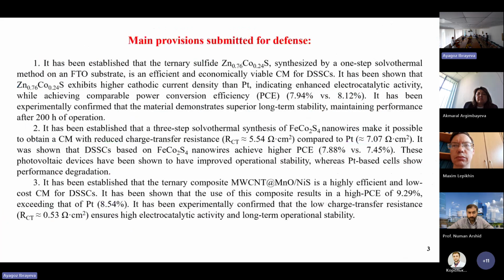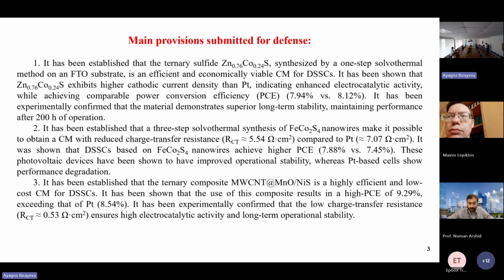Main provisions submitted for defense. First, it has been established that the zinc cobalt sulfide synthesized by a one-step solvothermal method on FTO is efficient for DSSC. This material demonstrated great long-term stability. The second, by another synthesis, it was established that iron cobalt sulfide nanowires work well compared to platinum, and also reduce charge transfer resistance. The third, a synthesized ternary composite of manganese oxide and sulfide with multiwalled carbon nanotubes showed higher efficiency than platinum. It has been confirmed that the low charge resistance provided high electrocatalytic activity and stability.